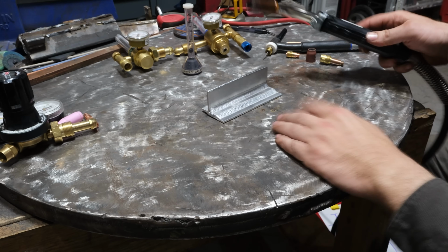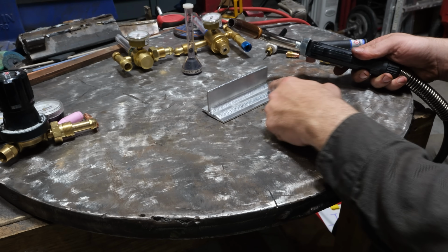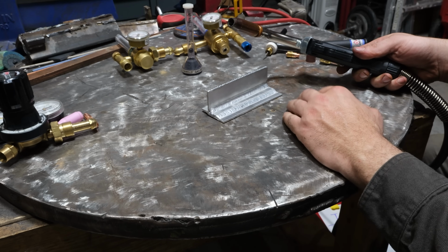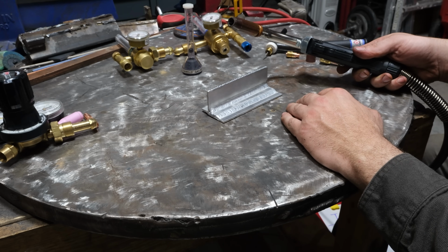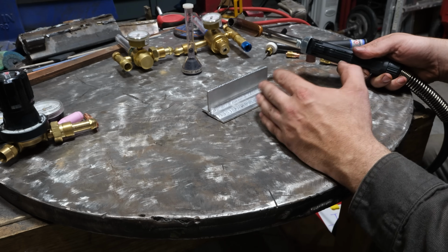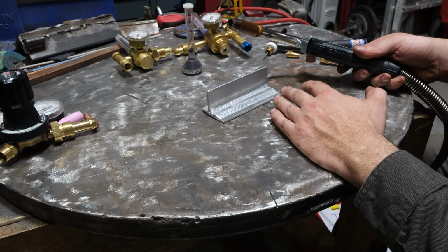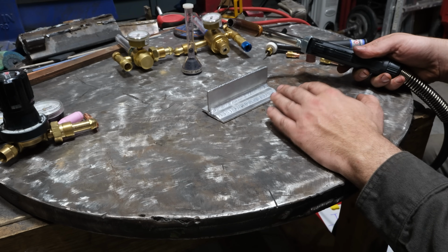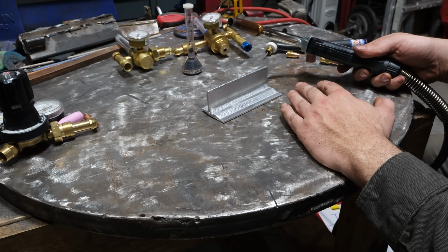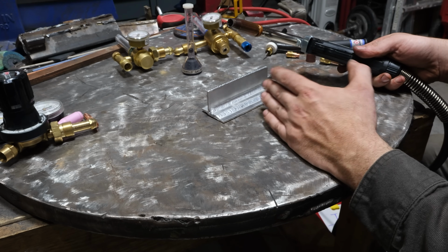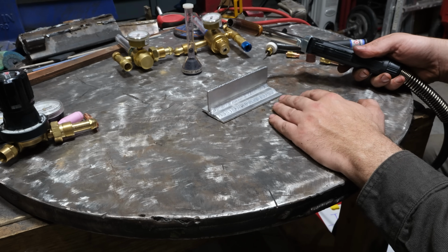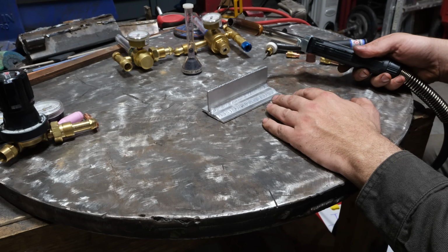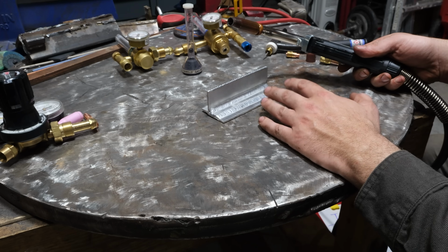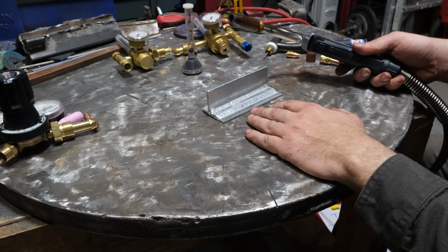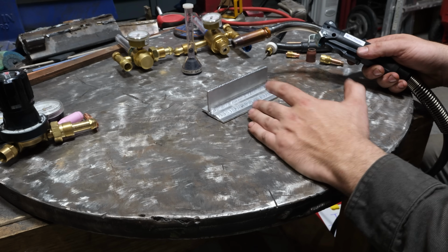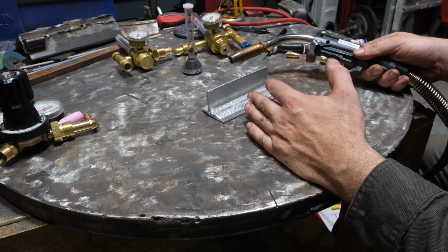Now, joint style matters, like I said. If you're welding fillet welds, experiment and drop the flow a little bit until you start seeing porosity and then bring it back up. I mean, the biggest problem is that if you drop it too low, you're going to have undesirable porosity and weld defects. The puddle won't flow well, and it's going to typically look grayed out or nasty looking, and those are things you generally don't want, so there is a lower limit on flow. But if you know you're doing fillet welds, back it off a little bit. If you're doing outside corner joints, bring it up a little bit.